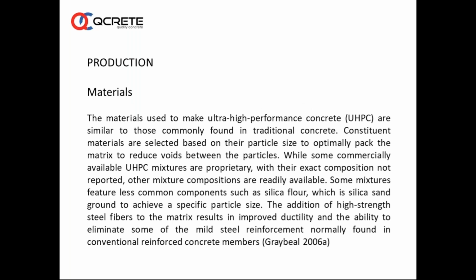The materials used to make ultra high performance concrete are similar to those commonly found in traditional concrete, and UHPC materials are selected based on their particle size to optimally pack the matrix to reduce voids between the particles. While some commercially available UHPC mixtures are proprietary, with their exact composition not reported, other mixture compositions are readily available. Some mixtures feature less common components such as silica flour, which is silica sand ground to achieve a specific particle size. The addition of high-strength steel fibers to the matrix results in improved ductility and the ability to eliminate some of the mild steel reinforcement normally found in conventional reinforced concrete members.